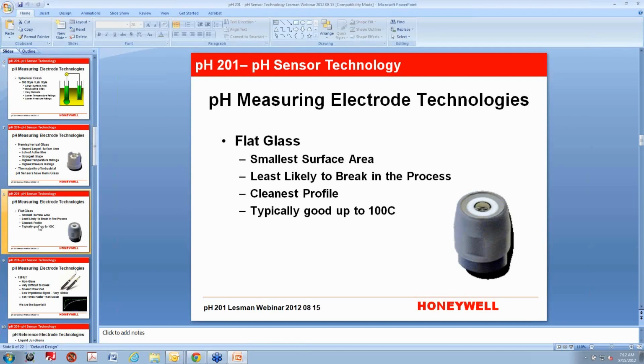These are typically good only up to 100 degrees C. Some of our hemispheres go up to 140 C. In fact, in a different body style, we can actually do 150 C, which is the highest temperature rating in the industry. But anyway, flat glass is good up to about 100 degrees C.